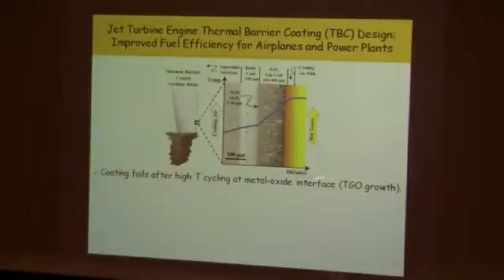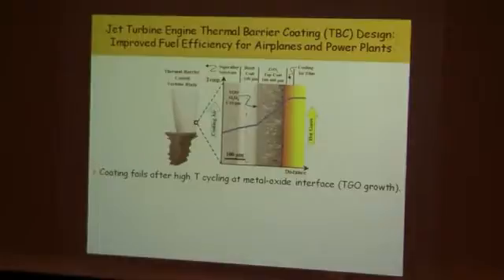And they fail at a particular interface between a metal alloy and an oxide, which is called a thermally grown oxide, this TGO. All that means is that under the operating conditions of the engine, an oxide grows in. This is actually alumina, Al2O3, that grows in. And once it gets too thick, there's a mismatch between the metal and the oxide that essentially makes the whole coating come off. And of course, you'd like to not be in the air when that happens. I'm not trying to scare you.